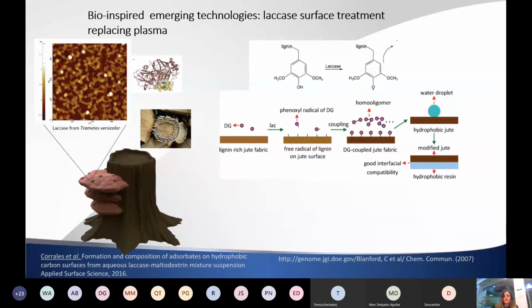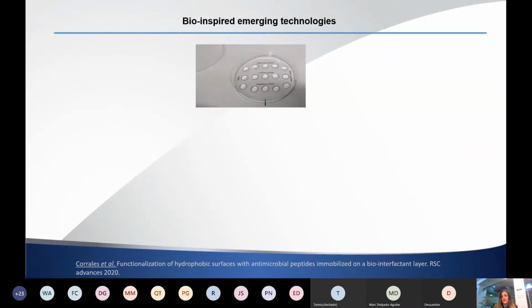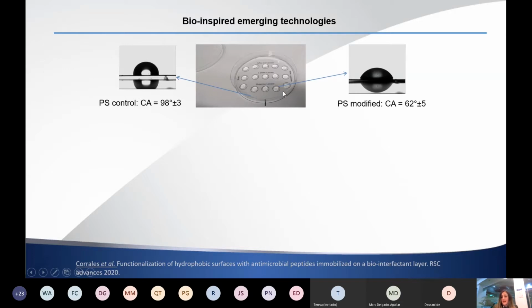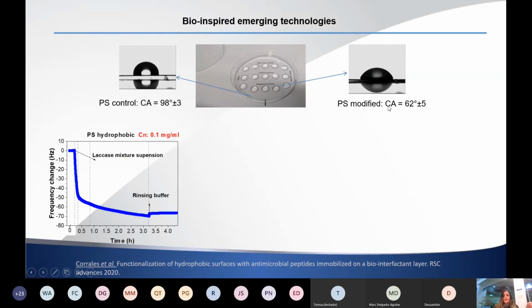We looked at the enzyme and we saw that 60% of the sequence of the enzyme are hydrophobic amino acids. So this enzyme is set in nature to have a good interaction with hydrophobic surfaces. So we thought, in the beginning, maybe as it is a polyphenol oxidase, it will oxidize the surface of a common plastic like polystyrene, and we treat the surface. We see these drops with the solution. After the drops dry, you see the polystyrene is hydrophobic, and after the treatment with laccase, it gets hydrophilic.